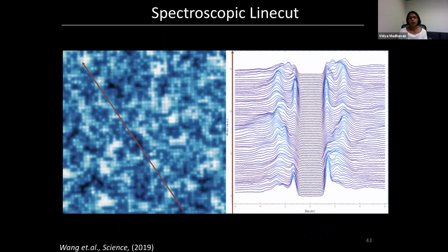Okay, now let's measure the density of states. And I already showed you what you should expect. This is a superconductor, so you should have 0 density of states at the Fermi energy, and then you should see sharp coherence peaks. So if you measured spectra along this line, then that's what this is. This is actual data. So let's just focus on the first point. So here you can see the coherence peak, flat 0 density of states, and then coherence peaks on the other side.